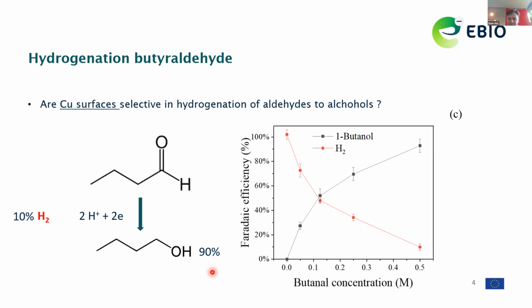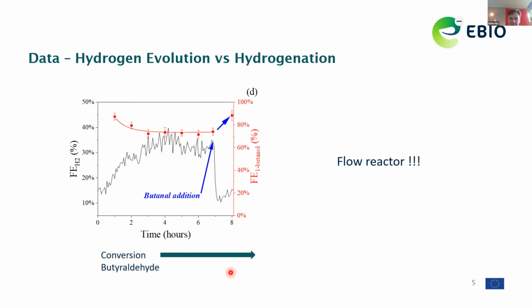Now, to complicate things a little further, of course you could look at double bonds as well. Before actually showing this, of course, if you have the concentration dependent situation, to make butanol, you could ask yourself, okay, in the course of the experiment, if it's a batch experiment, do you actually see the Faraday efficiency of hydrogen increase over time? And indeed, that's what we see. So here you see the hydrogen Faraday efficiency coming up, and that has to do with the conversion of the butyraldehyde in the solution. So as a function of time, we lower the concentration, and therefore we lower the Faraday efficiency of butanol hydrogenation as well.